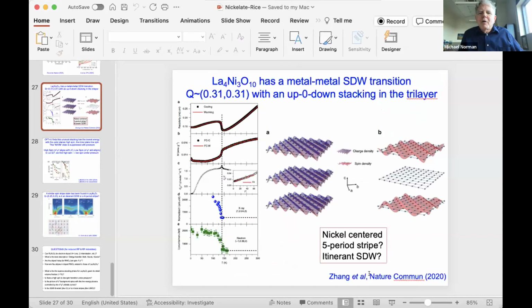The nice thing about 4310 is that fortunately, we were able to take this data before the APS went down. So we have tons and tons of data going out to high HKL. So the density wave state is known in great detail. The problem with the 327 is the crystals are very small, right? So it's not been as easy to get data on the 327. In fact, in 4310, we also have neutron data, right? And there's inhomogeneity of samples. So the samples are inhomogeneous.